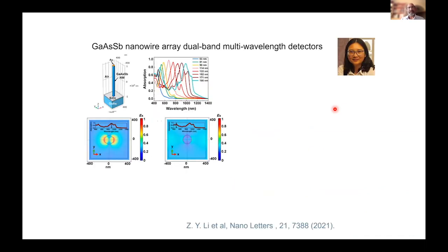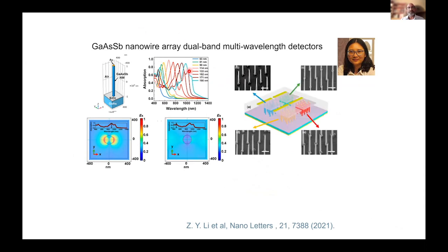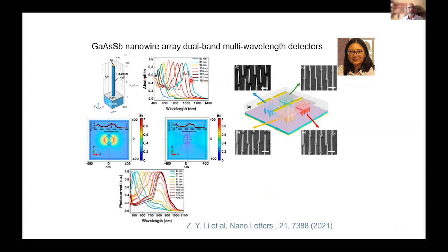Also, because these nanowires act like resonators, this is the work of my young colleague, Dr. Z.Y. Li. Basically you can change the diameter of the nanowire, and then the resonant wavelength can be shifted. This is a theoretical simulation showing that by changing the diameter of the nanowire, using the same material, the resonance changes. Here's a case where we've in fact fabricated these structures, putting nanowires of different diameters in these four regions here. And then you can show that you can tune the detection wavelength. So they could be very useful for multi-wavelength detectors, for example.